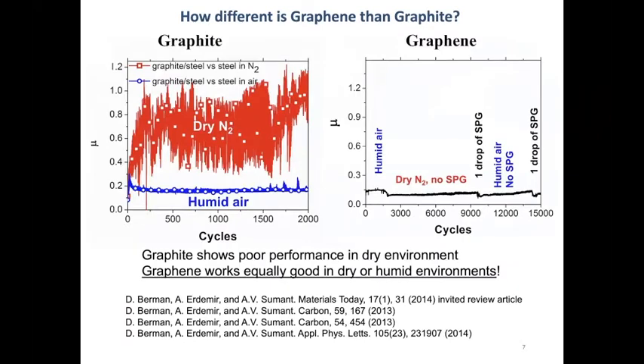And this is a summary of the comparison. You can look at the cited articles for better information on what is happening there. But comparing graphene, which is pretty much the 2D nature of graphite, in the case of graphite, you can see that in dry nitrogen environment, it's quickly eliminated from the sliding surfaces, providing high friction, which is pretty much the steel on steel dry sliding regime. In the case of humid air, that's what I mentioned for graphite, you get better lubrication stability and graphite allows the friction to stay at a pretty low regime, without much variation in the friction and wear.